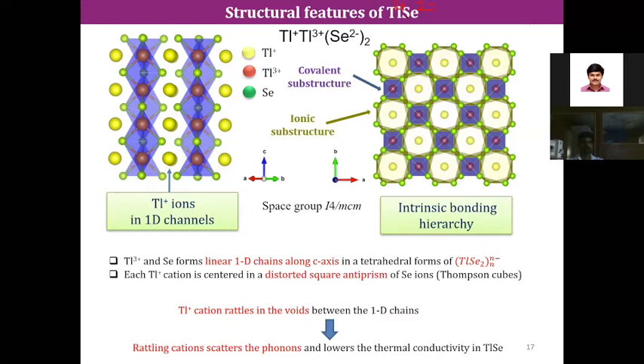And what I mean by these optical phonon modes, I'll go back to the slide. This is the optical phonon modes. You remember I said for a normal semiconductor, a normal solid, there will always be a gap between optical and acoustic. Now this thallium plus 1 rattling will lower the energy of the optical phonon, and we will have optical phonon very near to the acoustic phonon. So basically this optical phonon will scatter the acoustic phonon. That's what I mean to say here. So optical acoustic coupling or optical acoustic hybridization will happen, and that gives rise to ultra low thermal conductivity in this material. Okay, so that was the logic and chemical intuition we have from structural analysis.